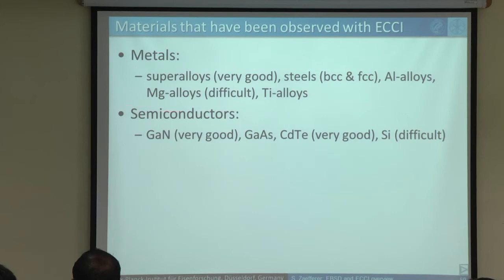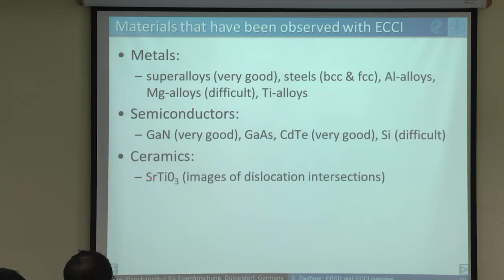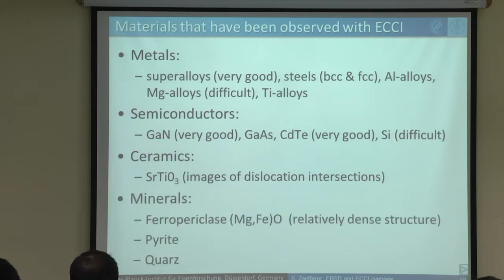Titanium alloys go well. We have done on semiconductors. Gallium nitride gives beautiful pictures. Also cadmium telluride, for example. Silicon is more difficult because, like magnesium, it's very light. It scatters very badly. Ceramics, we have looked on strontium titanate. More I have not yet seen, but I have looked in minerals. We looked in oxides of magnesium and iron. We looked in pyrite. We looked in quartz and some others. And it works everywhere quite decently.